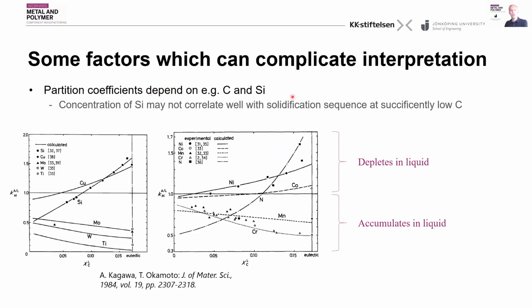So for example, the segregation behavior of silicon depends on the carbon content and the silicon content. So under certain combinations of carbon and silicon content, you can get quite strange patterns. The graphs below are from a study where they showed that the segregation of silicon and copper, for example, increases as the carbon content increases. It's a bit of a difficult unit on the horizontal axis here. It's atomic %, but you can see that they have marked where they have the eutectic composition. So when we have an increasingly hypoeutectic material, we can note that silicon segregates quite differently.